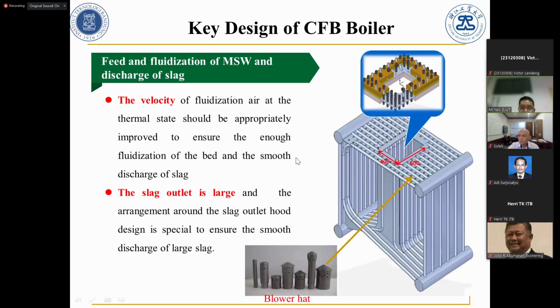And we use a larger slag discharge. So this is the blower hat. The air is blown to the bed through these patterns, different kinds. And here we use larger, 400 millimeter to 600 millimeter. That means the slag can be discharged smoothly. Otherwise it blocks here, then we have to stop it and open this discharger.